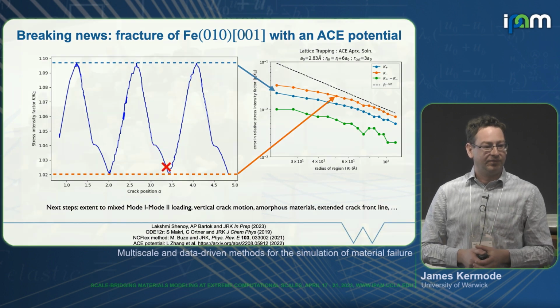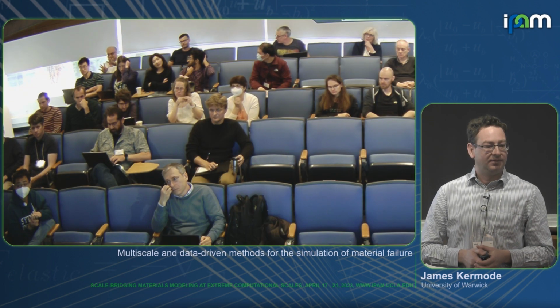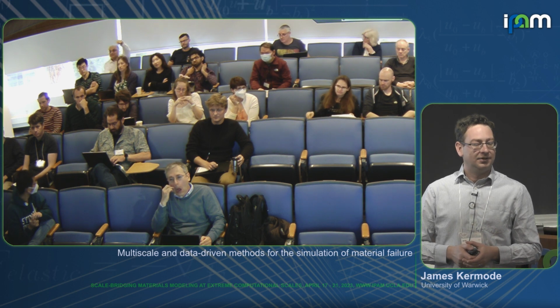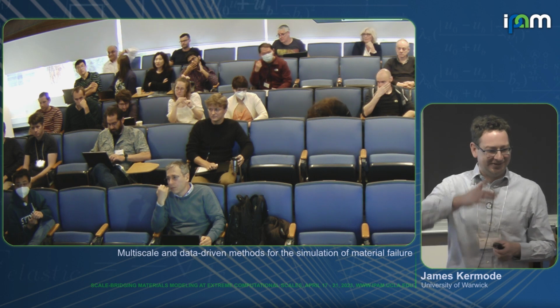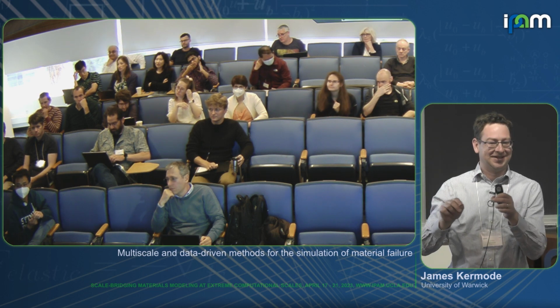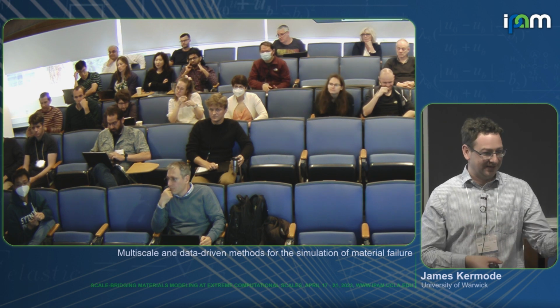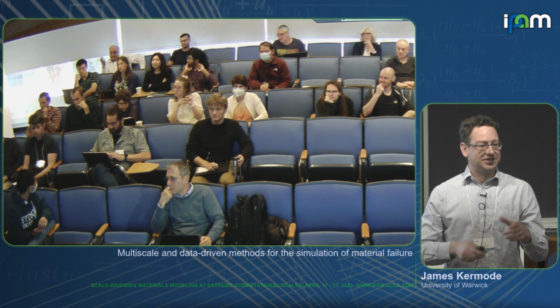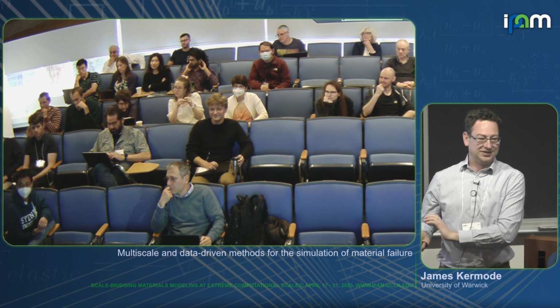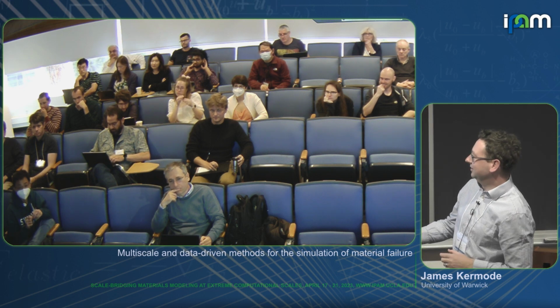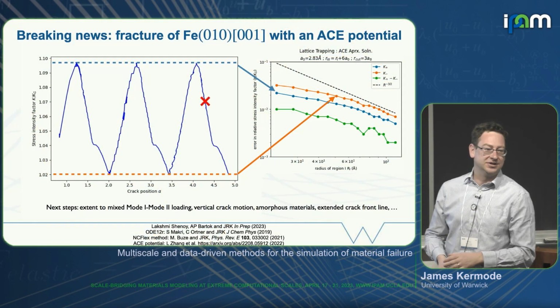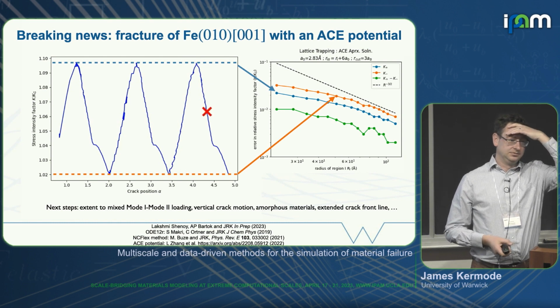The energy barrier you could just get from a stable grid. But I think you answered my question. You don't necessarily have to go through the unstable bit to get that. I don't know if you've tried to do these calculations. They're very fiddly to set up if you don't have something that can follow these paths, because, as I've said, the solution jumps, which makes it hard to calculate the barriers. And so it's really nice to have something where the barriers come out directly for all K. So as a function of K, we can just read off barriers from this single calculation.